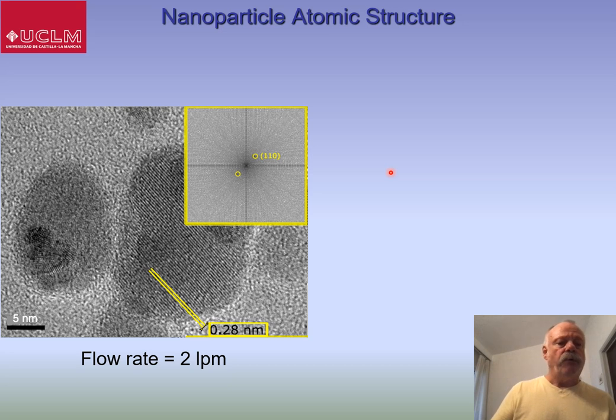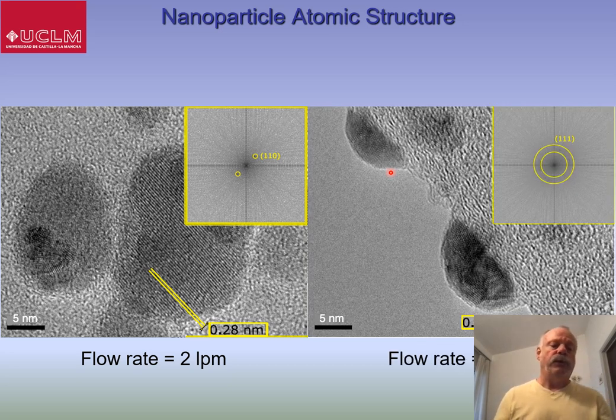That's our low flow rate. If we go to a high flow rate, we seem to get predominantly polycrystals, as shown by these rings of spots corresponding to the 111 silver lattice planes. And the reason I mention this is that this crystallinity does seem to have an effect on the antiviral performance.